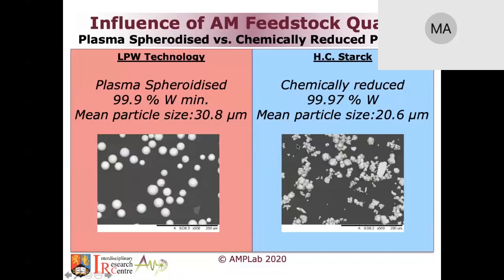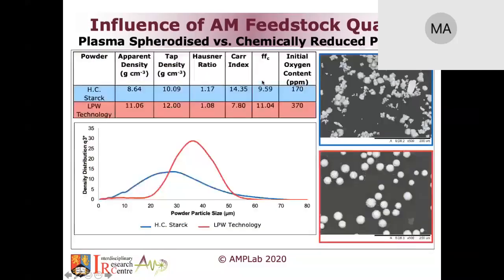So the key question was, if we are making that component where we're not bothered if we have some cracks, we're not bothered even if we have some porosity, as long as we can block some of the X-rays, as long as the part has some reasonable mechanical or structural integrity, which one of them can we use? So what we did with that, we compared both particles, and as you can see, the powder that comes out of chemical extraction has a lot of fine particles, and those of you who work on additive manufacturing know that having too many fine particles is not always great.